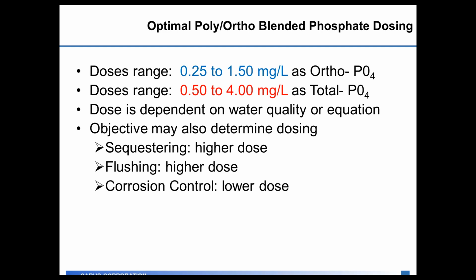The doses for an ortho-poly blend are a combination of the two dosages you saw earlier. Typically, you'll see anywhere from a 1/4 part to 1.5 parts as orthophosphate, and then anywhere from a half a part to 4 milligrams per liter as total phosphate. The difference between the total number and the ortho number is how much polyphosphate you would have in the system. Your dose is going to be dependent on your water quality for your situation and what type of blend you are using. So typically higher dosages would be if you're sequestering in the distribution system, and if you're just looking at corrosion control, then you would typically be on the lower end of that scale for dosages.